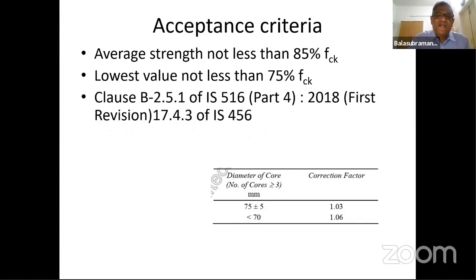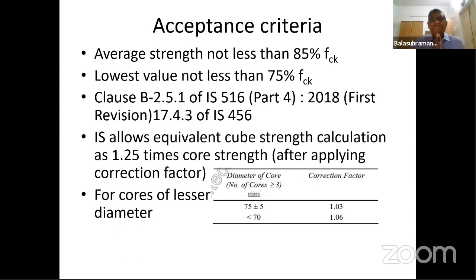Then what is the acceptance criteria? Now the IS code says, suppose you are testing 6 cores or whatever number of cores, the average should not be less than 85% of the FCK, not the target strength, FCK. And no individual core shall be less than 75% of the FCK. For example, if you take an M30 grade concrete and you have taken 3 cores or 6 cores, average should be 0.85 times 30, which is approximately 25.5. And no individual core shall be less than 0.75 into 30, which is 22.5. This is what the IS code says.